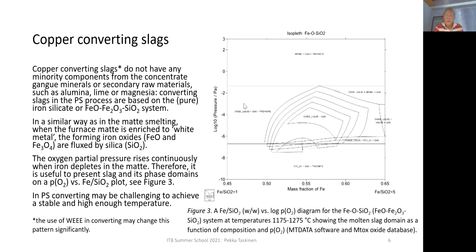So these kind of diagrams can easily explain to you how converting is carried out, and in which areas of the slag system you are. Are you in silica saturation? Are you in magnetite saturation? Are you in homogeneous slags? Are you in heterogeneous slags? Why the viscosity is low at some point, and why it is high in some compositions or oxygen potentials, oxygen partial pressures.